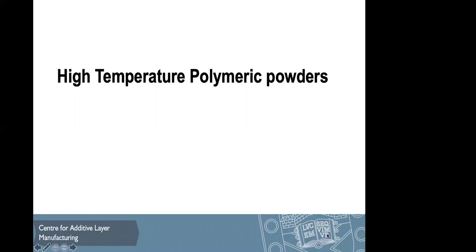It was a good powder, but had some faults, in a way that once used, it cannot be reused. The temperature was affecting the powder so much that the powder could not be reused, and that was a problem. A very big problem in manufacturing, as the cost of the components was extremely high. That was with the fact that the powder was degrading, really, and the cost of the material was very high.